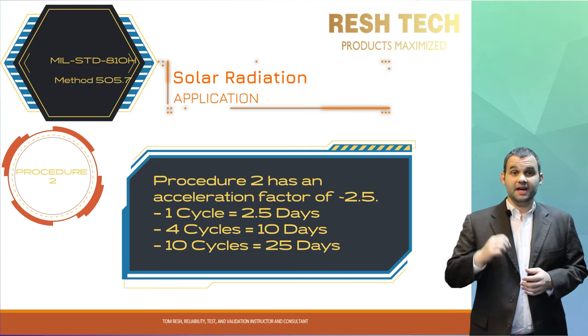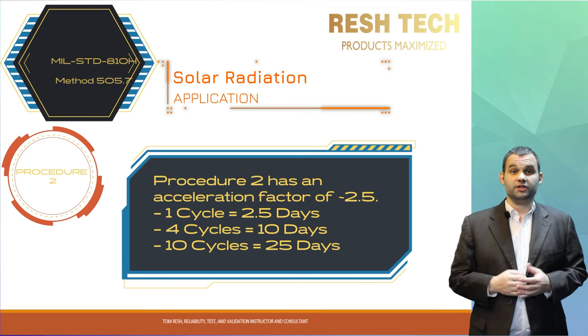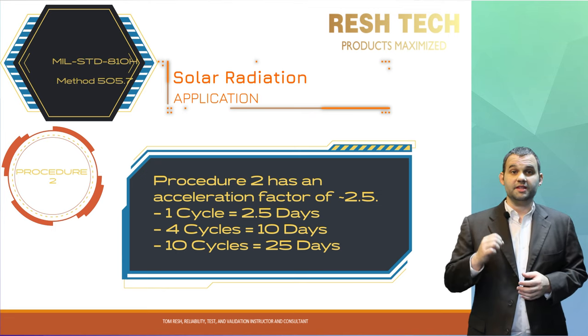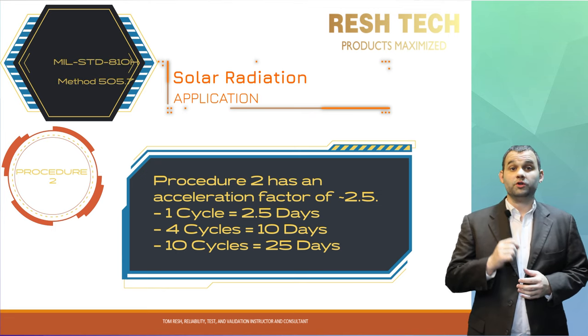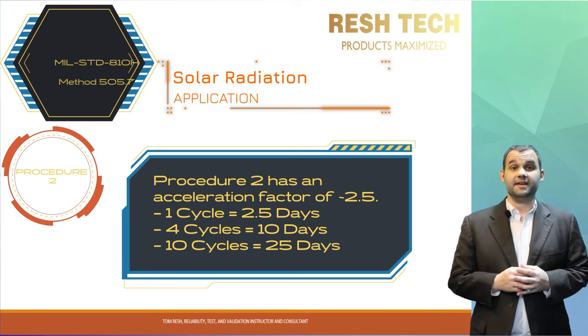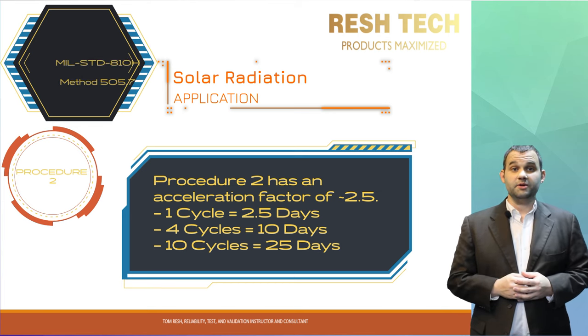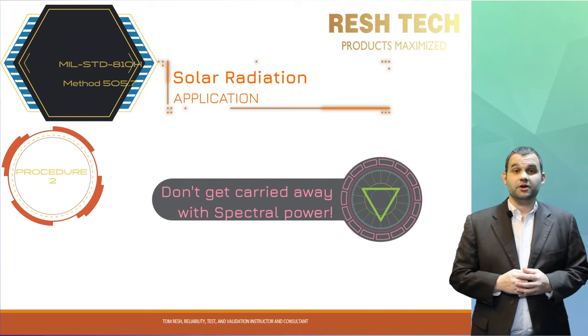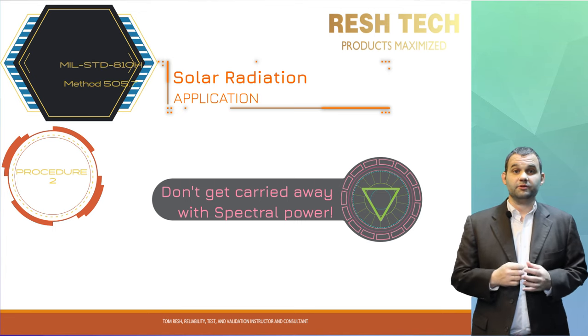What does this mean? It means that one cycle would simulate 2.5 days of natural exposure in the system's operating environment. 4 24-hour cycles would simulate 10 days. 10 cycles would simulate 25 days, and so forth. MIL-STD-810H cautions not to increase the spectral power any higher than the recommended levels in an attempt to accelerate the test further.